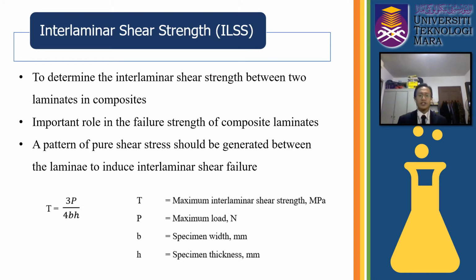What is interlaminar shear stress for? It is to determine the interlaminar shear strength between two laminates in composite. The interlaminar shear stress plays an important role in the failure strength of composite laminate. The interface can be sheared apart in the corresponding direction. When the transverse shear load experienced by the composite exceeds the interlaminar shear strength, a delamination failure occurs between the layers of the reinforcement fibers.